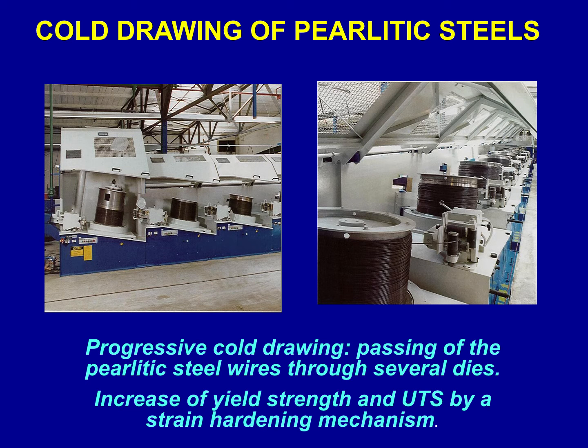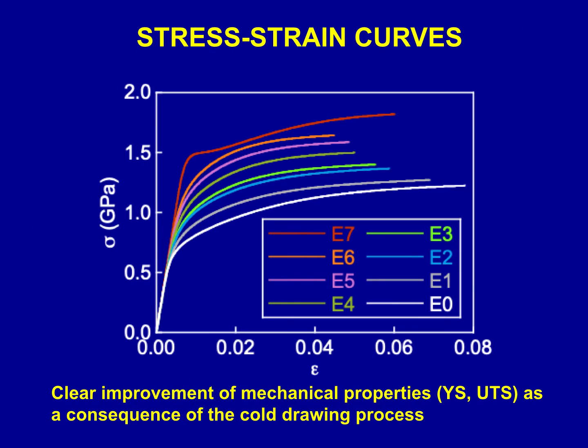Cold drawing of pearlitic steel is shown in these two figures, two pictures of the real manufacturing process in the company, with progressive cold drawing consisting of passing of the pearlitic steel wires through several dies, an increase of yield strength and ultimate tensile strength by a strain hardening mechanism, with stress-strain curves representing in the plot stress versus strain, with a clear improvement of mechanical properties, both parameters, yield stress and ultimate tensile strength, as a consequence of the cold drawing process. You see from steel 0 in white color, not cold drawn at all, to the steel 7 that has undergone 7 steps of cold drawing.